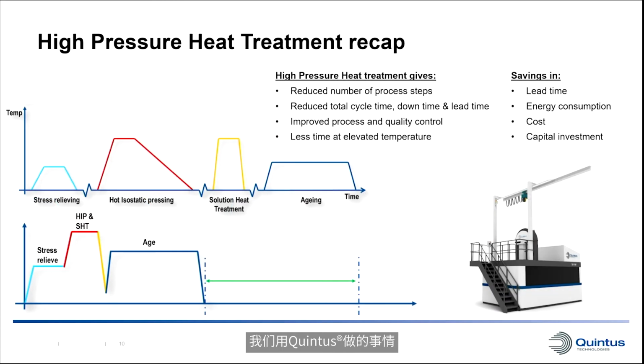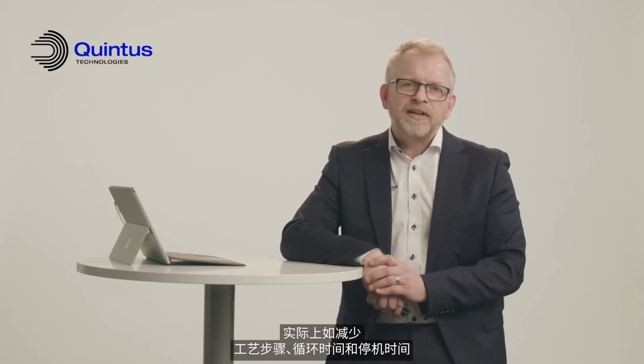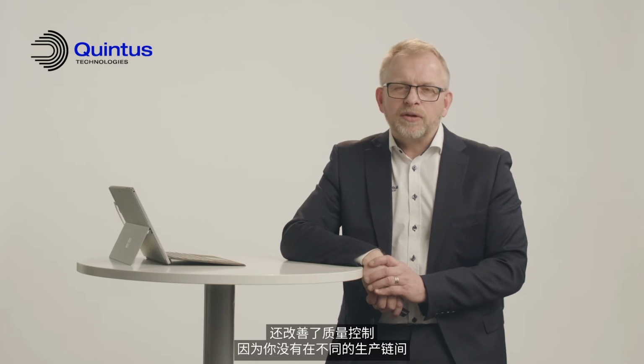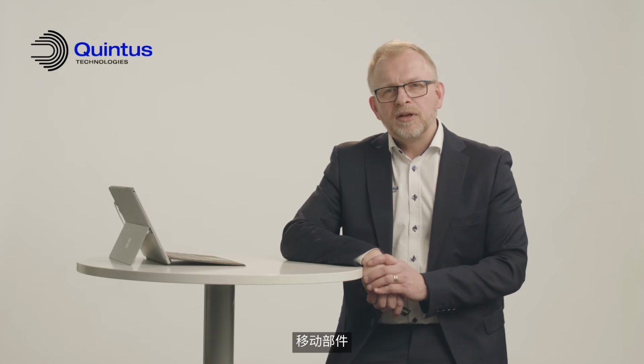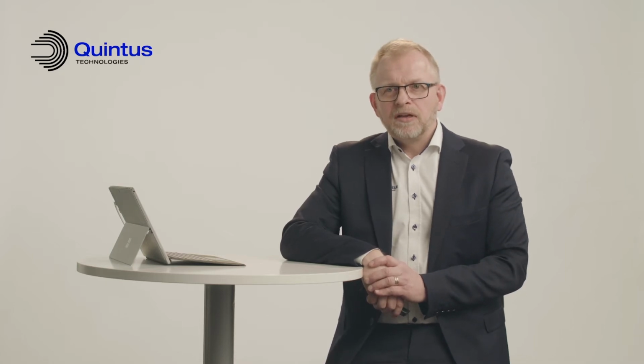What we do at Quintus is actually combine these into one process. So we do this in the HIP, using the cooling and actually steering the cooling to achieve the right material properties in one shot. This gives a lot of advantages actually, such as reduced number of process steps, cycle time and downtime, of course, but also improved quality control because you're not moving the parts between different parts of the chain.